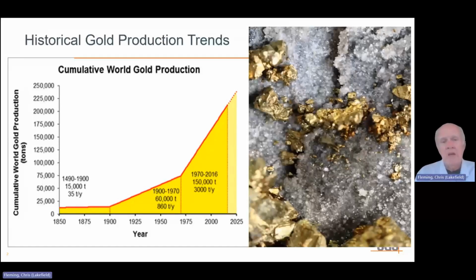And the main reason it had such an impact was that it was extremely efficient. It recovered not only coarse gold particles, but all the gold down to the finest particle sizes. So recovery efficiencies went from less than 10% to well over 90%. And as a result, the grade of gold ore that could be economically treated came right down.